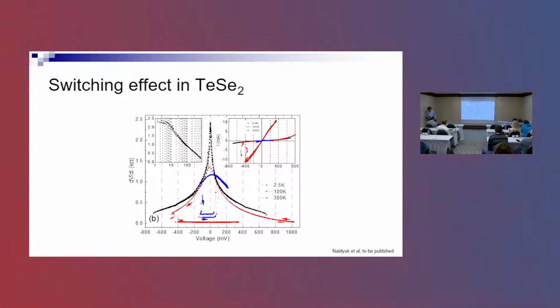And this is a semiconductor type of curve. So basically, we will stay forever at this semiconductor state. I'm saying something like semiconductor, but definitely this is exactly what people see in semiconductors, this type of behavior of resistance versus the voltage. And what is interesting, applying the opposite direction, we switch back to this low resistance state and can stay here. So this is like a switchable effect, which appears because of the response to the current.